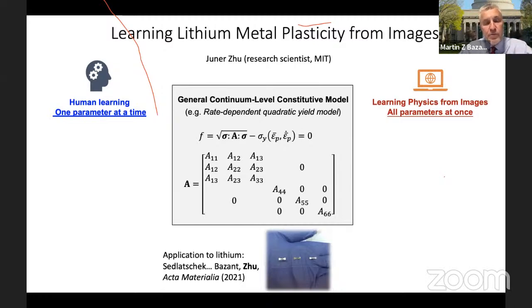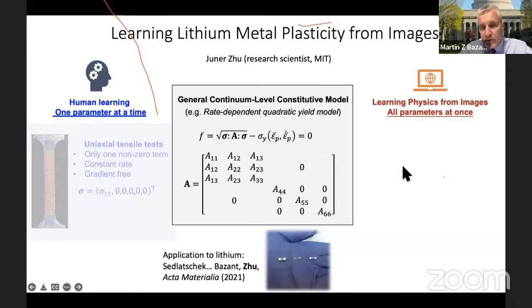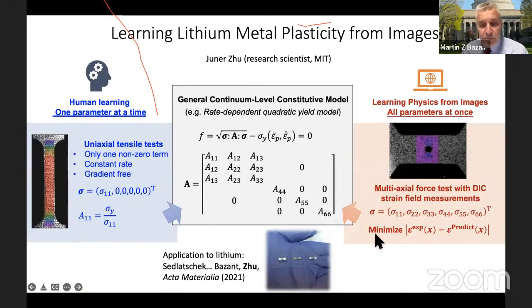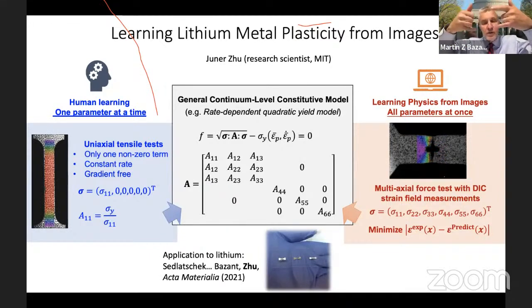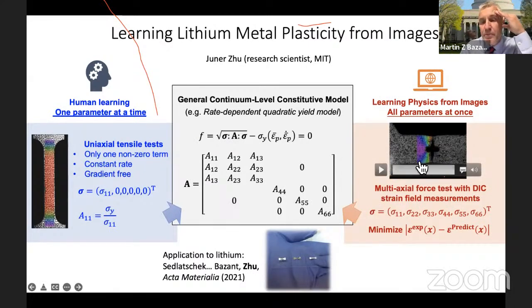And in this paper, 2021, we got, I think, the best results for lithium. For lithium mechanics, nonlinear plasticity like this, by doing simulations like this, we took a foil of lithium, put some shaped notches or holes in it, pulled it apart, and from digital image correlation, we have the strain field. And by essentially doing a finite element calculation of the mechanics and solving an inverse problem, we can learn the coefficients in this quadratic yield model.